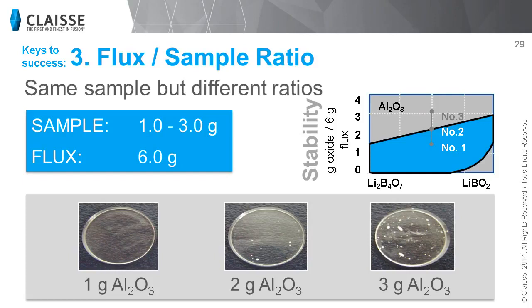As shown in the previous table, all oxides have a limited solubility in borate flux. We can see here an example with alumina. When we change the sample to flux ratio and we keep all the other factors identical, we can see that we don't obtain a homogeneous glass disc when going from 1 gram of sample to 2 grams of sample, which is over the alumina oxide solubility limits in the 50-50 lithium tetraborate, lithium metaborate flux. As expected, the quantity of undissolved particles is even larger when using 3 grams of sample in the same quantity of borate flux.